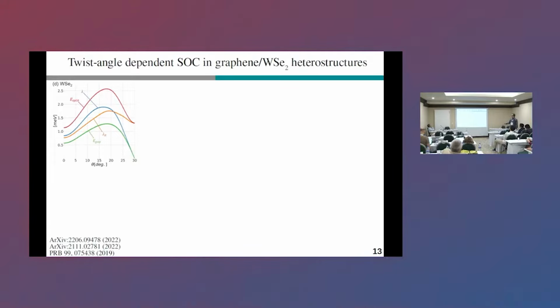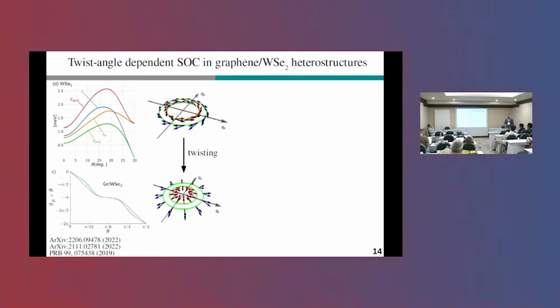The Rashba spin-orbit coupling does not show such a, say, nice evolution. It stays more or less the same over the whole twist angle range. And on top of that, the Rashba spin-orbit field, this in-plane spin-orbit field, can be heavily deformed by twisting. So it has been shown that at 0 degree twist angle, you have such a tangential typical Rashba field you would expect, but once you twist it to a certain angle, it can become purely radial.